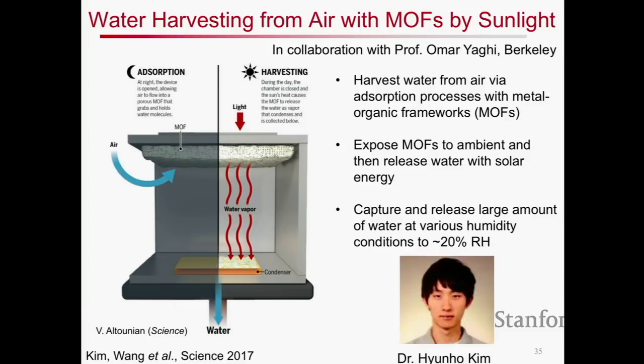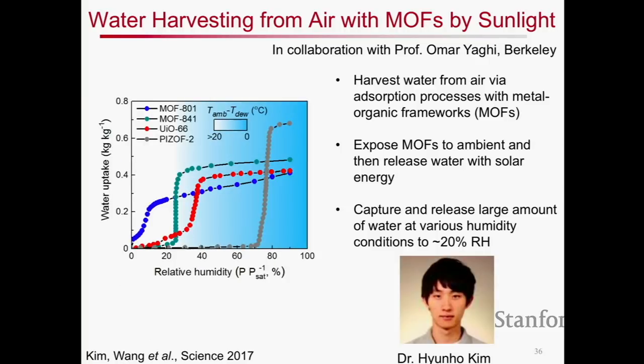While the concept seems relatively straightforward, my student here really led this effort, working with Omar's students, and thought about how we can take advantage of these metal organic frameworks that have a unique kind of characteristic. What I'm showing here is an isotherm. This is a water uptake as a function of the relative humidity. There are certainly different types of isotherms for these various types of adsorbent materials. Because we were interested in the low relative humidity range, we looked at isotherms to see how we can capture water when there's a nice sharp step, say on the order of 20% relative humidity or so.